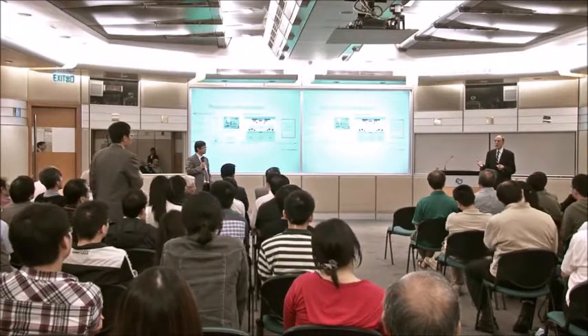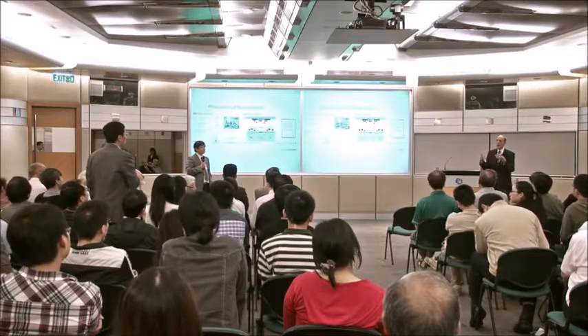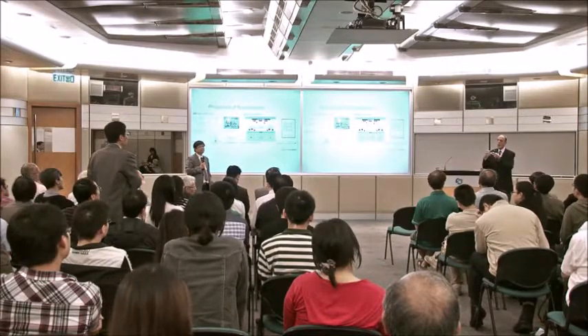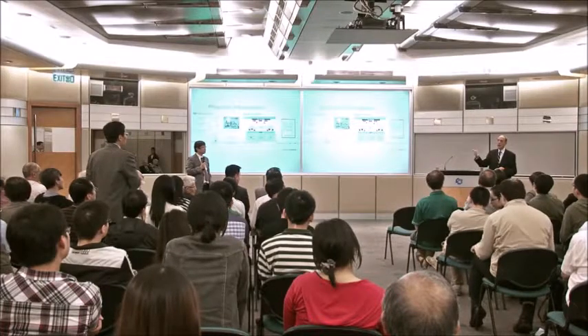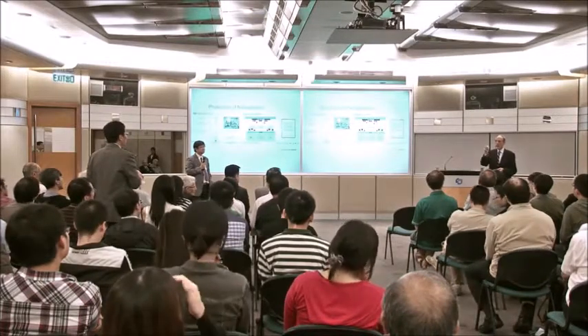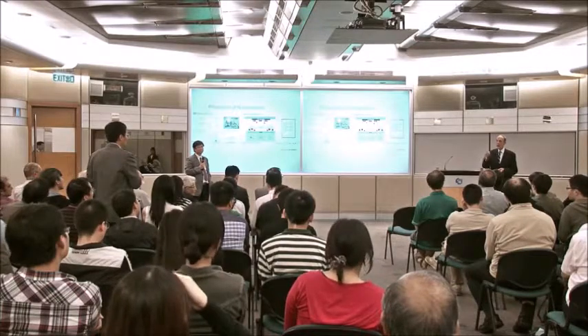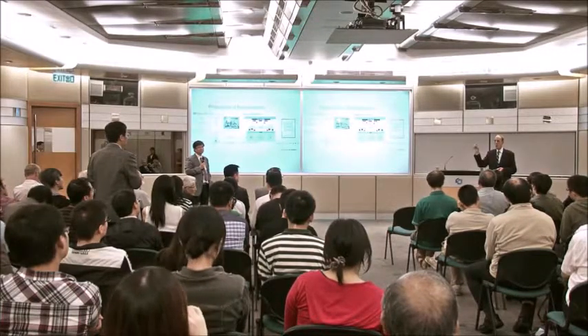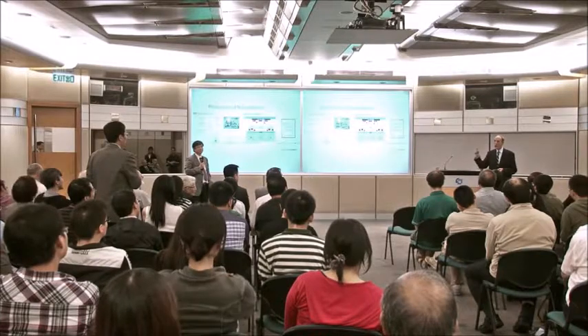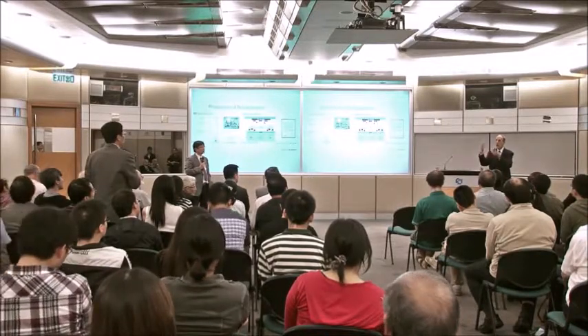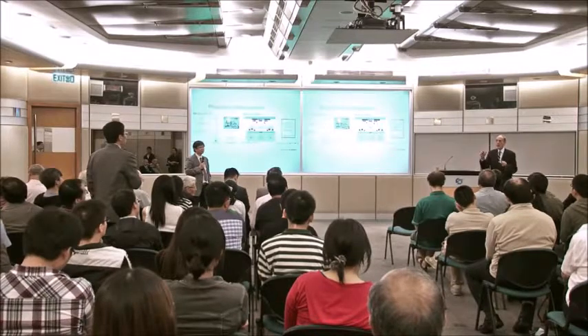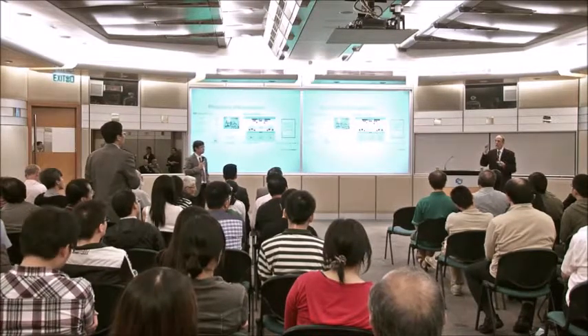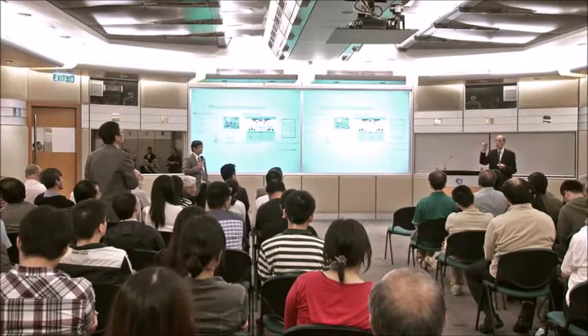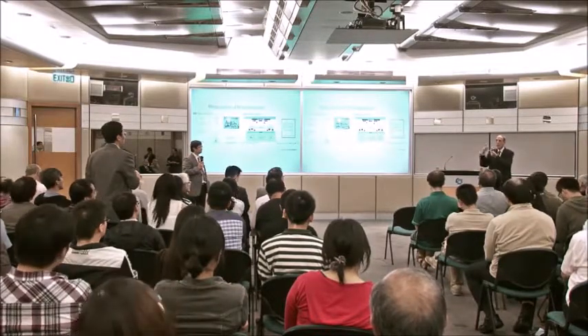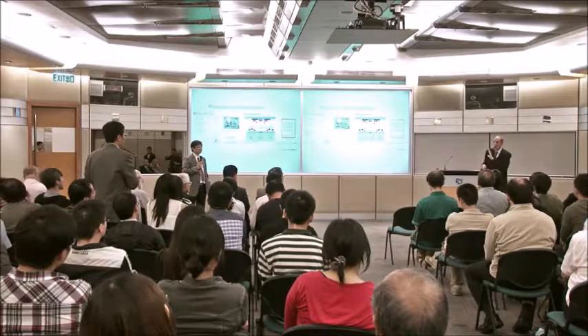Our problem is, when you want to do any kind of understanding, you have to know we have two kinds of interaction. The interaction between the atoms in the glassy region, and then the interaction in the interfaces. And the trouble is, as we don't know at the moment the detailed structure of the interfaces, we cannot understand that interaction. We can measure modulus, we can measure diffusivity, mobility, but this is always a summary. We don't know what the nearest neighbors look like, and what the average spacing is, if it's larger or smaller. That is our whole problem. You can describe it that way. It's the same thing, yes.